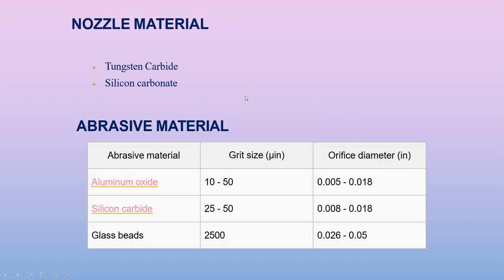And the nozzle material normally is made of tungsten carbide or silicon carbide. For abrasive material aluminum oxide, the grit size is 10 to 50, and the orifice diameter is 0.005 to 0.018 inch. And for silicon carbide, it is 25 to 50 grit size, micro inch, and orifice diameter is 0.008 to 0.018 inch. And for glass beads, the grit size is 2500 micro inch, and the orifice diameter is 0.026 to 0.05 inch.